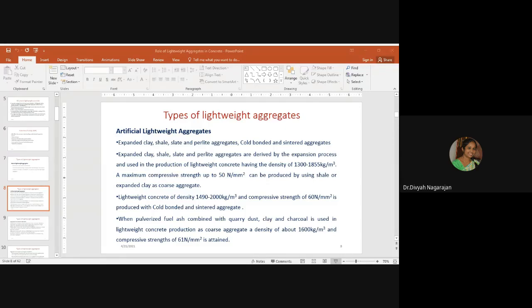Expanded clay, shale, slate, and perlites produce lightweight concrete having a density of 1300 kilogram per meter cube to 1855 kilogram per meter cube. A maximum compressive strength of 50 Newton per mm square can be produced by using shale or expanded clay as coarse aggregate. The cold bonded and sintered fly ash aggregates are produced using pulverized fuel ash or fly ash. Lightweight concrete of density 1490 to 2000 kilogram per meter cube and compressive strength up to 60 Newton per mm square are produced with cold bonded and sintered aggregate.